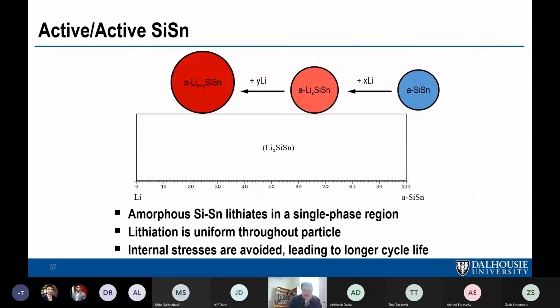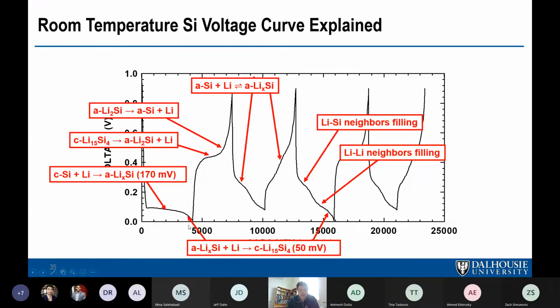One thing it's good to point out, especially in the case of silicon, is that often it's assumed that being amorphous means you have a single phase region, but that's not true. Amorphous materials can exist in two-phase regions with other materials too, just like the delithiation, if we go back here, when the crystalline 15-4 phase is delithiated, it forms an amorphous phase. You can have two-phase coexistence between a crystalline material and an amorphous material. So don't think that just because you're amorphous, you might be avoiding two-phase regions.